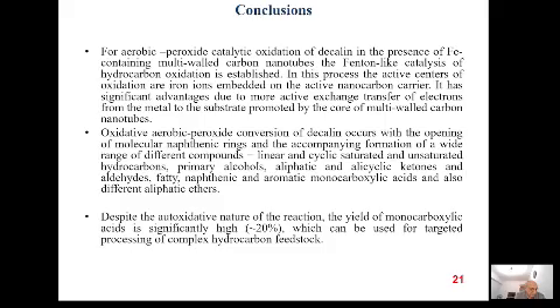Conclusions. For aerobic peroxide catalytic oxidation of decalin in the presence of ferrum-containing multi-walled carbon nanotubes, the Fenton-like catalysis of hydrocarbon oxidation is established. In this process, the active centers of oxidation are iron ions embedded on the active nanocarbon carrier. It has significant advantages due to more active exchange transfer of electrons from the metal to the substrate promoted by the core of multi-walled carbon nanotubes.